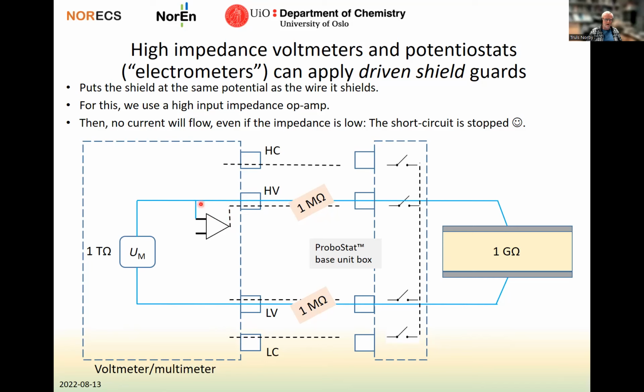Now we obtain, without drawing any current, the situation that the wire and the shield are at the same voltage. When they are at the same voltage, no current can run between them. Therefore, there is now no short circuit current anymore between them. So even if these are in contact with each other in a way, we can still maintain different potentials on this one, so that no current runs here, and no current altogether runs through the shields. So the shields are no longer a threat, no longer short-circuiting the wires. So they still do the job of shielding, but they don't short-circuit.